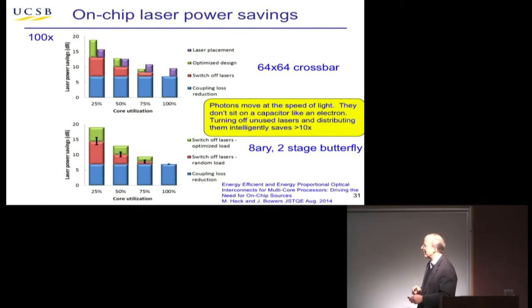So it turns out if you analyze this for different cases, take some energy efficient processing scheme, and there's two examples here, crossbar butterfly architecture. What do you gain by having the laser on chip versus off chip? It's somewhere between a factor of 100 and a factor of around, say, 6 or 7. So if you've got a multi-core architecture and the lasers are on, every core is on all of the time, you don't gain as much. But if you're turning off 3/4 of those cores, as one would do in some proportional computing scenario, then you actually save a lot. You save up here.